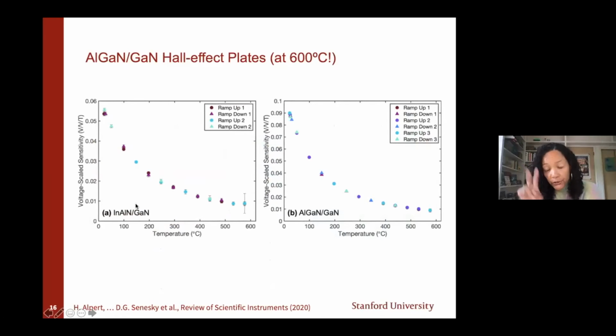So there's again our two iterations, our indium aluminum nitride on GaN and our aluminum gallium nitride on gallium nitride heterostructures. And so this is work from Hannah Albert, recent graduate from my group. What she was doing is operating at elevated temperatures in air and also ramping up and down. So you can see here heat cycling up and down, room temperature up to 600 C. We see this exponential decay. This actually corresponds to a decay in mobility, which is something that is very typical for most semiconductor devices, right? As you increase temperature, your mobility goes down. And so that translates to our voltage scale sensitivity very nicely. So that is something we expect.